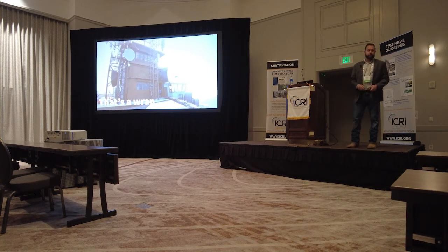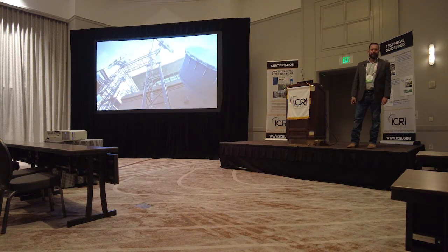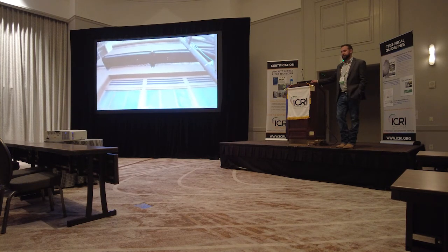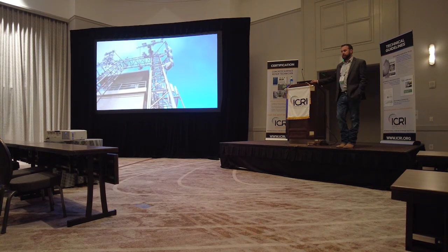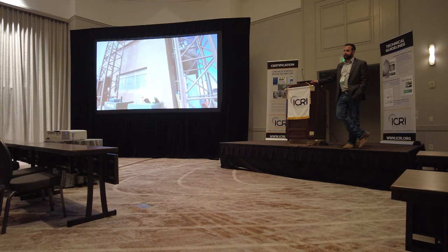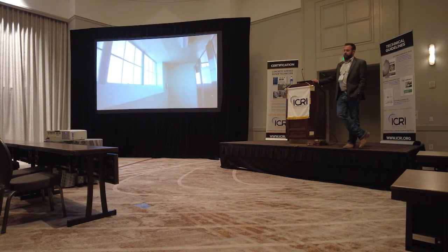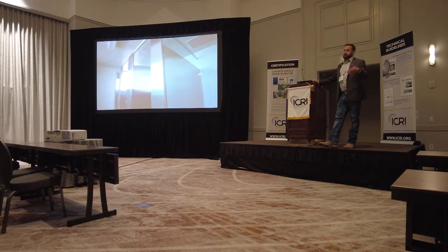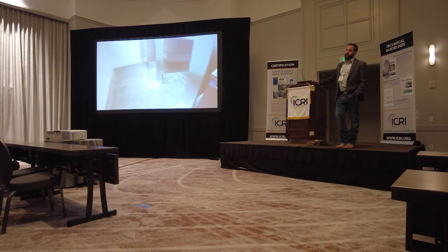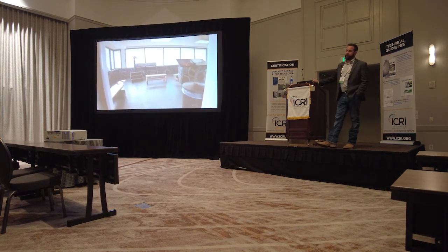And with that, that's a wrap — that's Mount Washburn. In the Q&A: on the original concrete at 576 PSI, what was the make-up? Was there fly ash? There was not fly ash. Was there lime? There was lime — that's exactly what it was. When going back with the repair mortar, was it more like a lime mortar to mimic the lime content? We actually sent it in for basically a petrographic analysis, did a mortar analysis, broke that down into parts, and were able to rematch it identically — pre-matched it, bagged it, brought it all up, and were able to mix on-site.